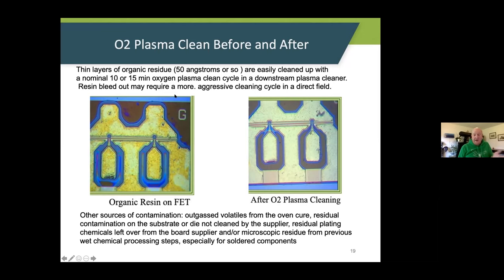And that's usually in a downstream. Most wire bonders put the unit in a downstream plasma cleaner. But you can get a little more aggressive if you need to. So outgas volatiles from the cure oven, residuals on the substrate. I've been involved in a few jobs there where nobody could wire bond anything. And that's because the way the supplier shipped them in, and or maybe they got repackaged in the factory and there was some residue on the Teflon boards or on the ceramic boards.